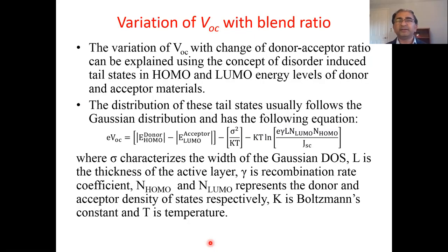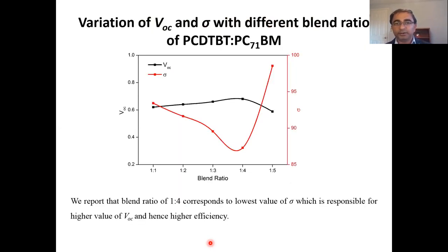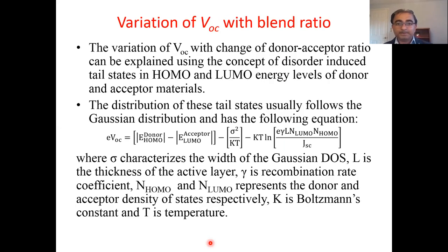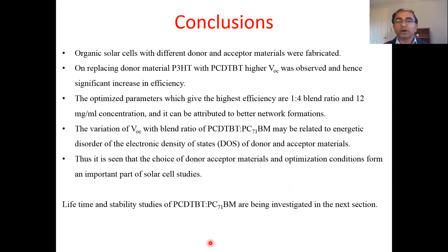Now, why is there a variation of VOC with blend ratio? We have to theoretically try to explain these variations. For this, there are density of states Gaussian curves. And there are some conclusions that the variation of VOC with the blend ratio is related to the energetic disorder of the electron density of states of donor-acceptor materials.